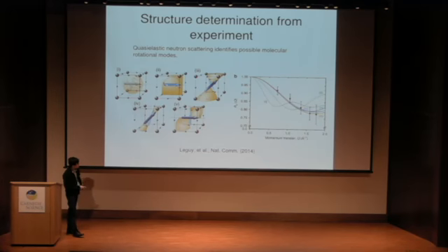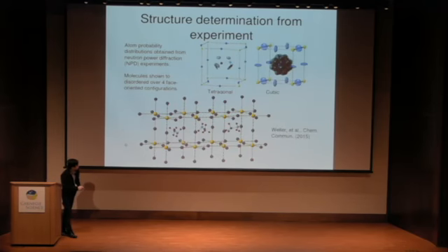In these neutron scattering studies, they have shown that there are many types of molecular rotational modes, and also, like we have just heard from the previous speaker, there are many possibilities in which the molecules can point. So it's likely that there's not just one single favored hydrogen bonding mode. In this somewhat more recent experiment from last year, they showed that in the tetragonal phase, they think there are 4 possible orientations of the molecule corresponding to 4 faces of the tetragonal cell. And in the cubic phase, basically, it can be pointing anywhere.